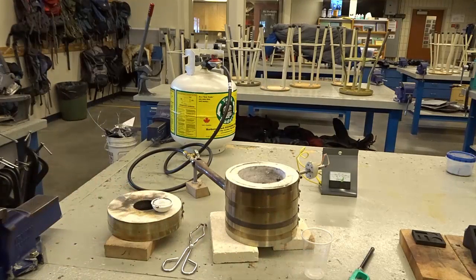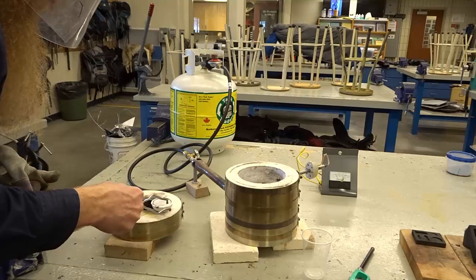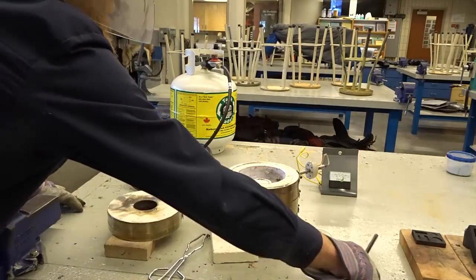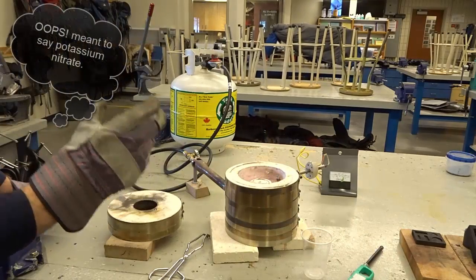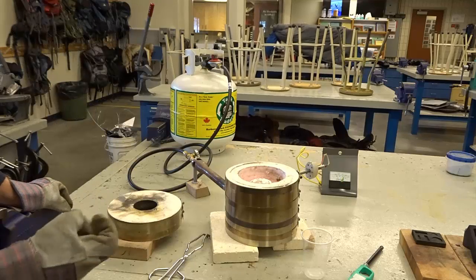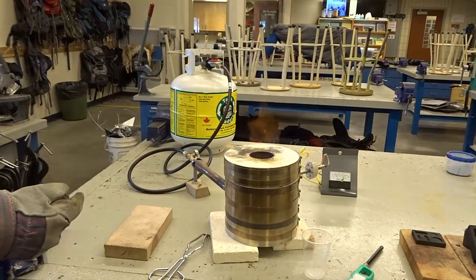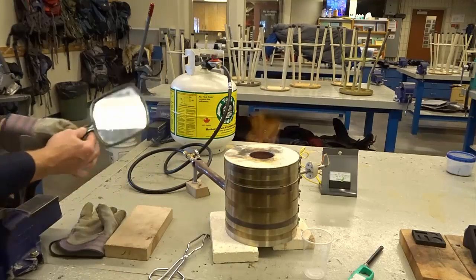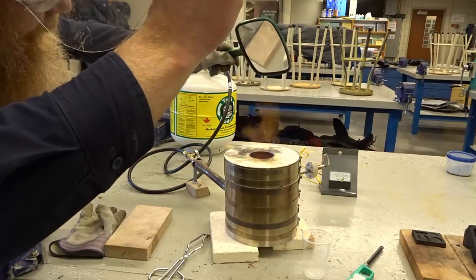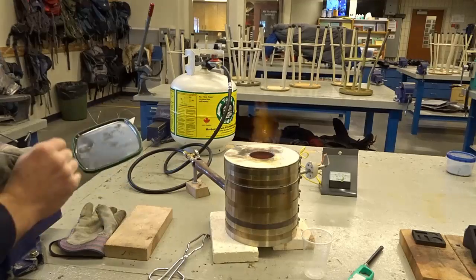A very, very full crucible. That will melt down and get a lot less volume very quickly. Without the potassium nitrate and with no sulfides in there, I don't have to worry so much about the flux boiling. That's why I'm using just a very small crucible. And now I just watch the temperature — I need to get over 2,000 degrees. Looking good in there. It was a little bit full but it's settling in its crucible nicely.